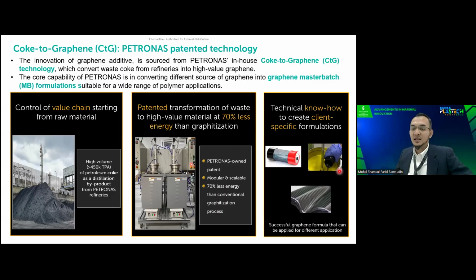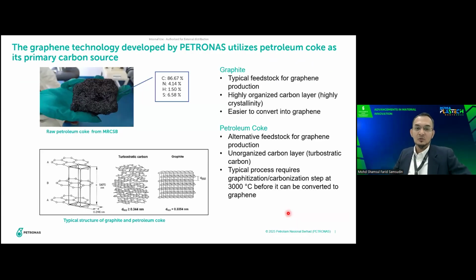At this moment, the target application for our graphene is for battery, coating, and also polymer composite. And this is how our petroleum coke looks. Most of the composition is carbon, around 86%, and the rest is impurity like nitrogen, hydrogen, and sulfur.